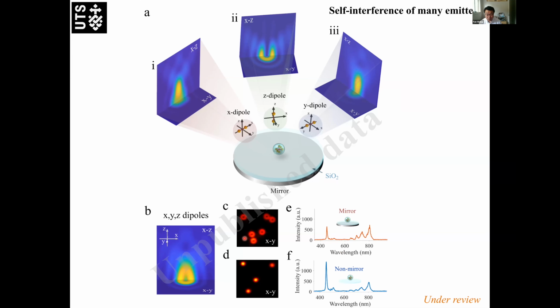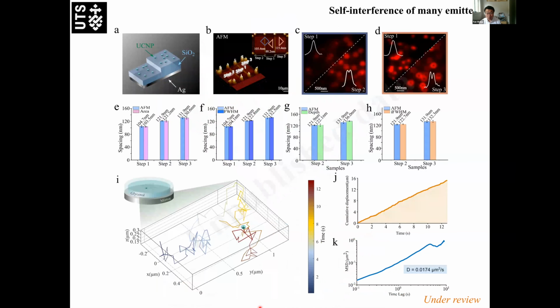For example, for this one, if you have destructive interference, you are going to have a hole in the middle of the PSF. And if you change the spacing, this pattern will gradually change. This change is really sensitive to the position, and it's not sensitive to the state. It's only sensitive to the distance between the emitter and the mirror side. It isn't sensitive to drifting and this kind of thing. Therefore, we can use it to do distance sensing, and also tracking.